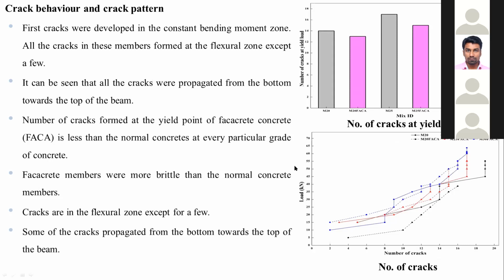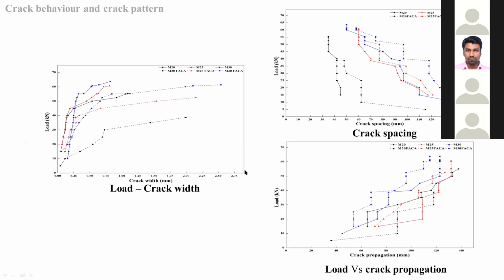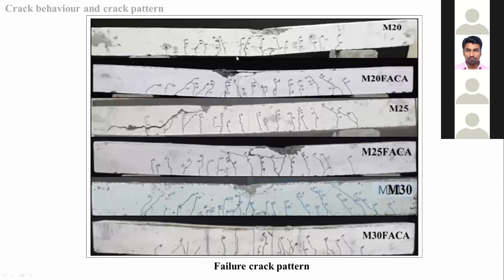We concluded that Facacrete members are more brittle than normal members. These are the crack variations: load versus crack width, load versus crack spacing, and load versus crack propagation. These are the failure patterns obtained for our specimens.